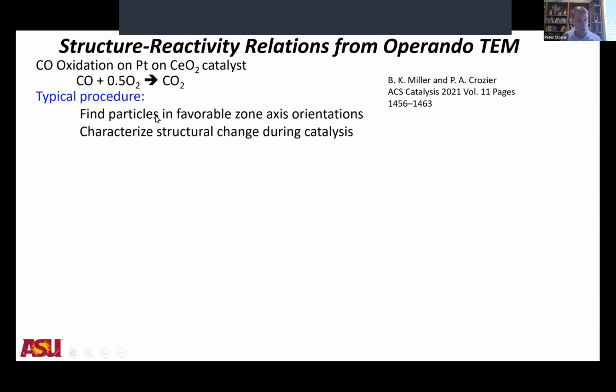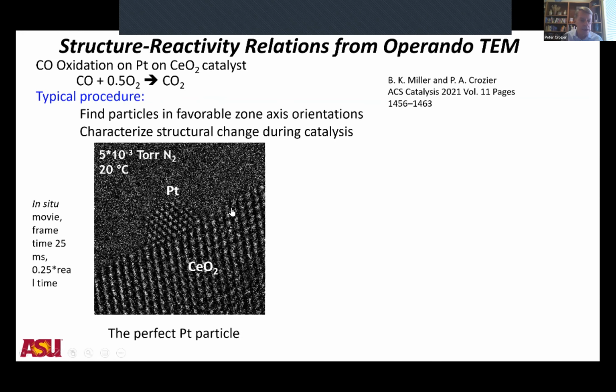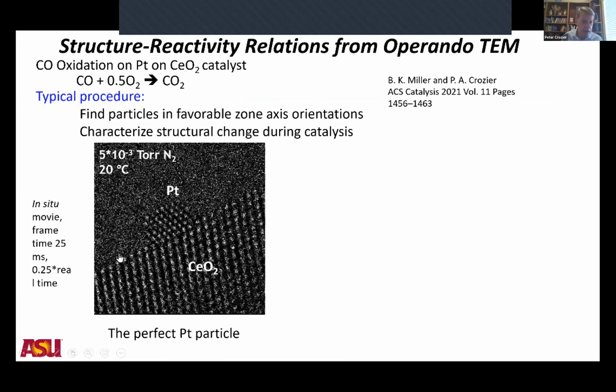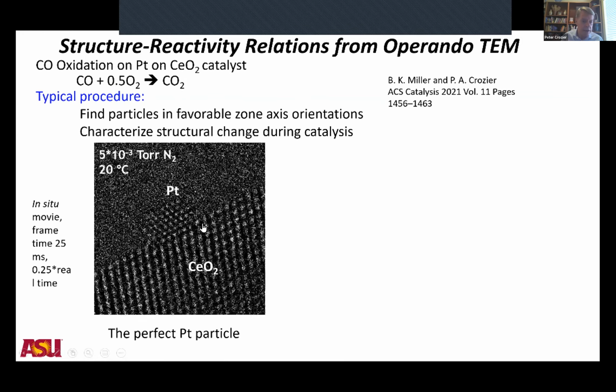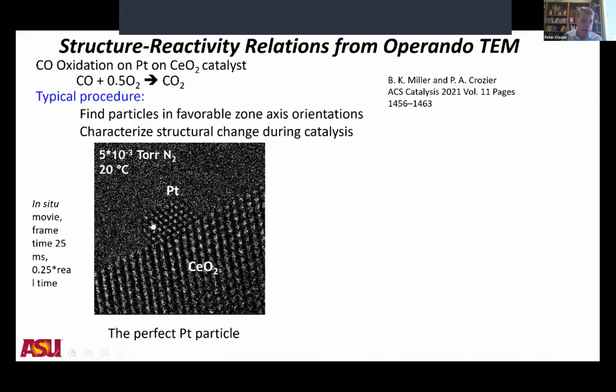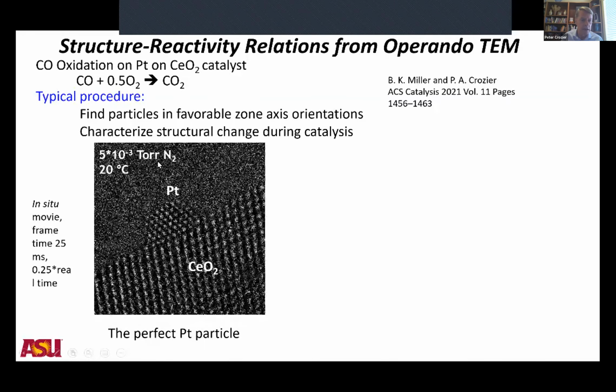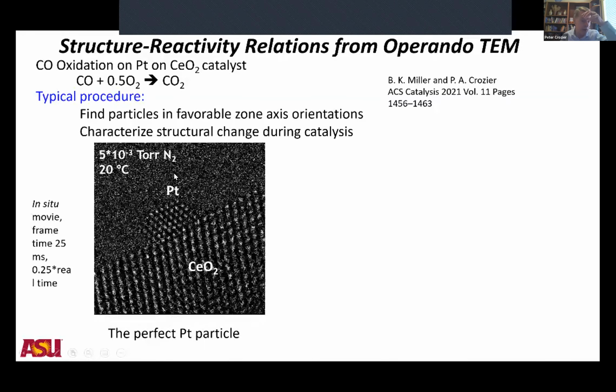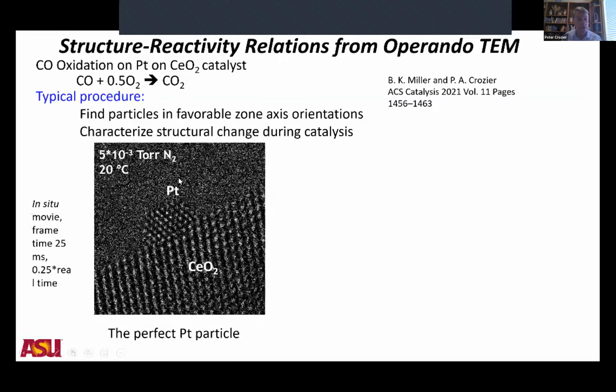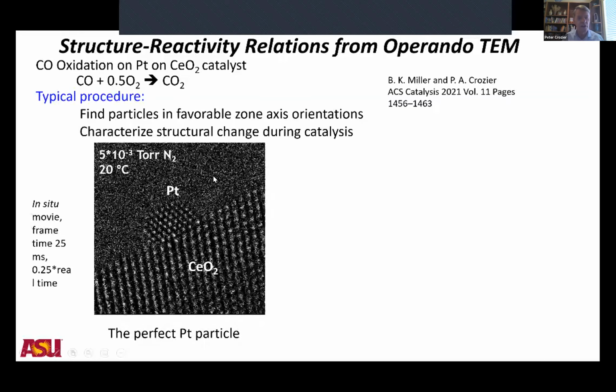Typically what you'll do is go to the microscope, find some ideal nanoparticles in favorable zone axis orientations, and then change the reaction conditions to those that are relevant to catalysis and look at what changes occur. So here's an example: a platinum nanoparticle oriented along a zone axis, this time in an atmosphere of nitrogen at 20 degrees Celsius. And so you would say, well, this is my perfect initial configuration.